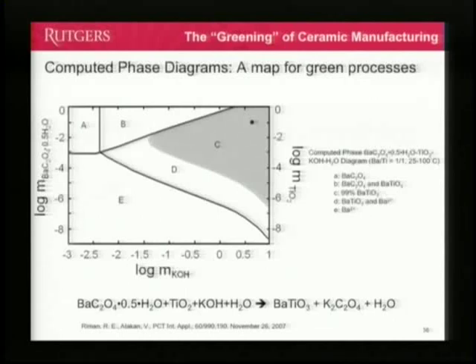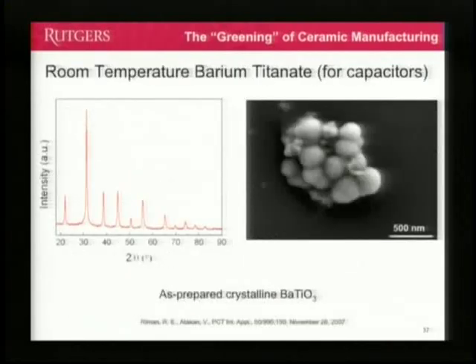And this is a room temperature diagram, so we were dying to find out if this thing actually worked. And lo and behold, in a few minutes, you can make barium titanate, straight from the same raw material that industry says can only be done at high temperature and milled. And here's some examples of the powders. This is a very good first result that shows we can make the particles small and spherical, and from here we can optimize a lot of the process.